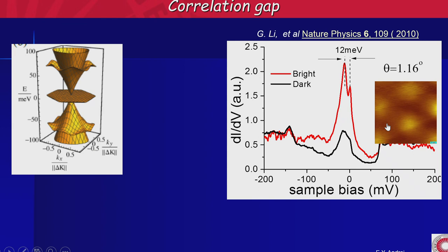So this is our data here. We actually were almost at the magic angle. We saw a gap opening at the Fermi energy of about 12 millivolts.